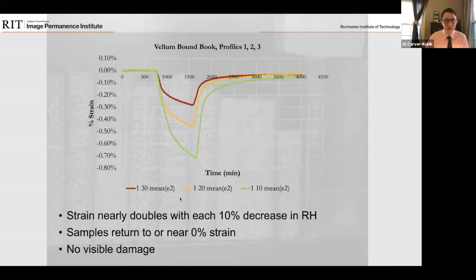So what we can see in this graph is the red line is the profile in which we went to 30% RH. The yellow line is when we went to 20% RH, and the green line is when we went to 10% RH. With each 10% decrease in RH, our strain nearly doubles. Again, this example is a vellum-bound book, but this was true for all of the books and all of the single sheets of material.